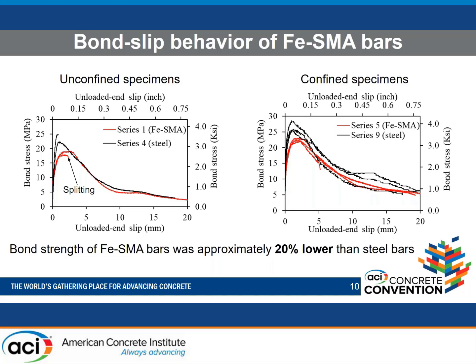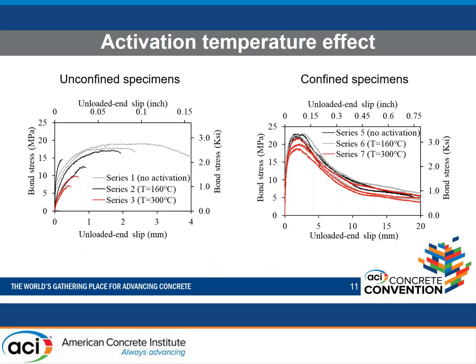So after getting the general behavior of the SMA bars versus conventional steel bars, we need to investigate the influence of activation temperature, which we said is very important for these types of bars. And what I'm showing here for no activation, for 160 degrees Celsius and for 300 degrees Celsius, this is for unconfined and this is for confined. Obviously, you can see major reductions in bond strength as you increase the temperature for unconfined specimens, while for confined specimens, there is not much reduction. For 160, it's almost similar to no activation. For 300, there's just maybe a 20% reduction, not more.